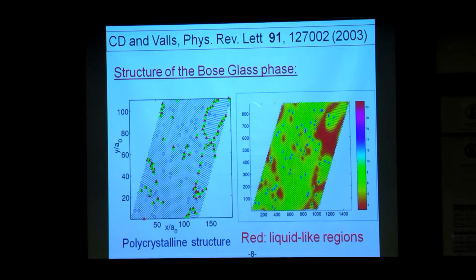This is the work that we are doing on the vortex system, and it was published some time ago. But we had the results from which we could see that it's a Bose-Glass phase. There's a polycrystalline structure. You can see here there is a big crystallite, and then there are other smaller crystallites separated from it by these grain boundaries. And one could see that the vortices which are near these grain boundaries behave like a liquid as compared to the vortices which are in the middle of the crystalline regions.